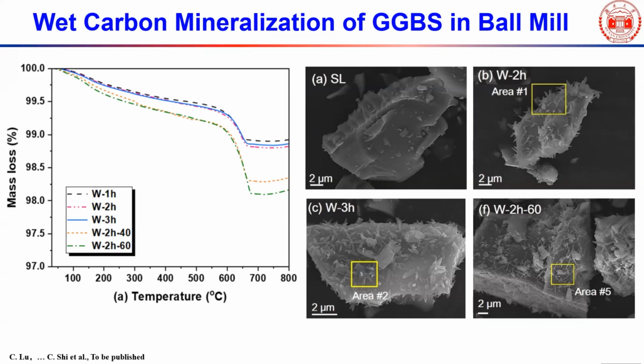It's very small. And in the SEM, we can see this is the original slag particle, this is after 2 hours, this is after 3 hours, and this is after 2 hours at 60 degrees C. You can see the surface carbonation is very, very limited, right? So this is really interesting. We are also working on that.